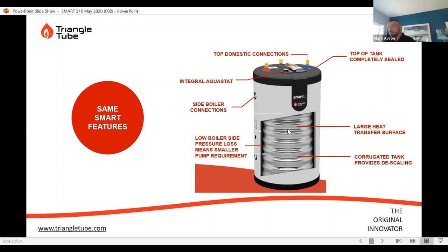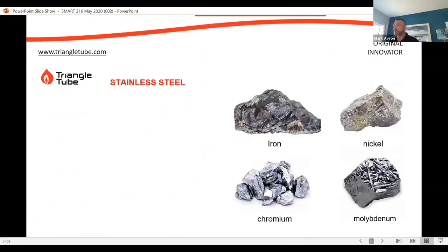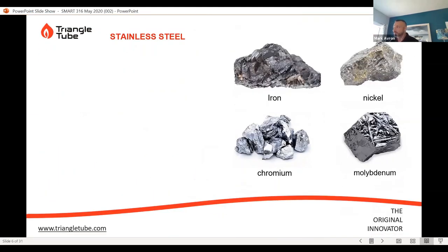So tank and tank design, the stainless steel 316 tank inside of an outer carbon steel tank. And that corrugation actually gives you a descaling feature. So as the tank moves, as it heats and cools and expands and contracts, it will help prevent scale from forming on the tank, which over a period of time is going to reduce heat transfer and cut down on the efficiency. So talking a bit about stainless steel, right?